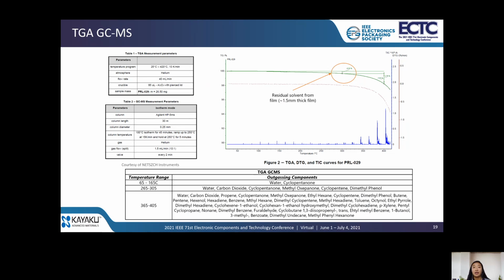So a thick film was created at CAM and outsourced to NETZSCH for TGA GCMS testing. The film dimensions were 4 millimeters in length by 4 millimeters in width and 1.5 millimeters thick. The test was ramped to 420 degrees C at 10 K per minute. PRL29 had around 1.4% weight loss at 400 degrees C. However, some of the initial weight loss in the beginning is believed to be residual solvent left in the film, since the film was so thick. 1.5 millimeter film thickness is not within the operating range PRL29 is designed for.